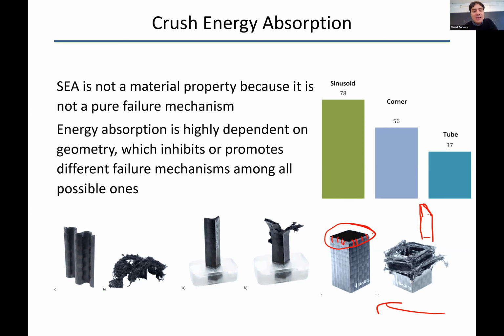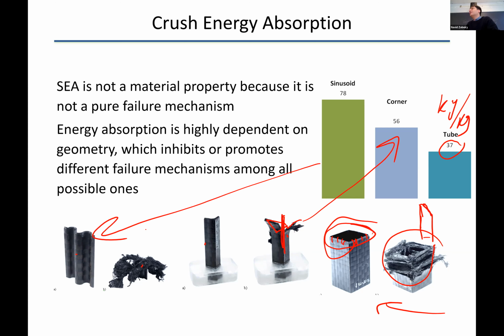Anyway, there are lots of details in the test, but they realized that if they change the design, the energy absorption capability changes significantly. If you have a tube, the energy is around 40 kilojoules per kilogram. Still much higher than aluminum or steel. If you have a corner, there's still one corner that fails in tension, let's say, and you start bending the other component, but it's still better than a tube. So it increases the energy to around 50 to 60. And the best case scenario is something like this, which doesn't have a sharp corner, because there is no corner to break, and then the rest will go to bending. So you will start crushing everything. So you can increase the energy to around 80 kilojoules per kilogram. So the design has a significant impact on how much energy you can absorb.